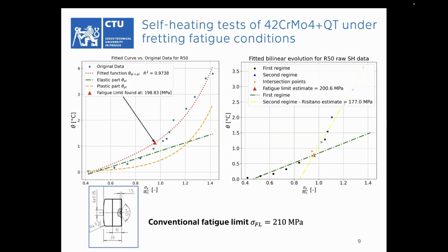Here on this axis is a normalized stress amplitude, normalized by the conventional fatigue limit. So the point 1.0 should demonstrate if the prediction or experimental evaluation finds the fatigue limit there, that there is an ideal match between the self-heating method and the conventional fatigue test. In the case of our approach, there is 5% difference, approximately the same we can say for the Luong's method.